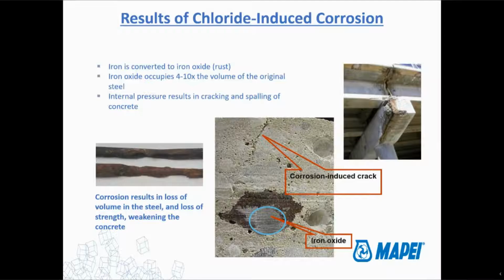What happens is the iron gets converted to iron oxide. We touched on that before. And when that happens, the iron oxide, or the rust as we call it, actually takes up about 4 to 10 times the volume of the original reinforcement steel. So it kind of expands, if you will, as the rust starts to form. It takes up more space, and by taking up more space, it starts to impart a tensile force on the concrete. As we know, concrete is very, very strong in compression, but it's just not very good in tension. That's why we use the reinforcement steel in the first place. So as you create those internal pressures in the concrete, that creates that tensile force, which causes the concrete to crack because it's being overstressed. So it cracks to relieve itself, and then those cracks typically will lead to spalls down the road as the cracks spread and take out a big chunk of concrete, and then you get that falling concrete problem that we're trying to avoid.